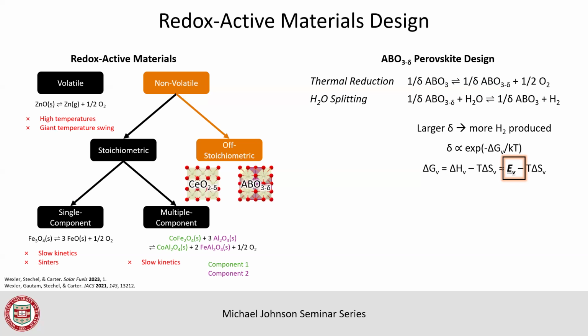Now, how do we increase the amount of hydrogen we can make? Well, we design materials that can release more oxygen when they're heated up. Because if they release a lot of oxygen and then are presented with water, it's like, give me all that oxygen, right? So the better it is if it can release a lot of oxygen when it's heated up. And basically the amount of this delta, or amount of oxygen that gets lost from the material when it's heated up, is going to be related to the free energy to form a defect in this crystal.